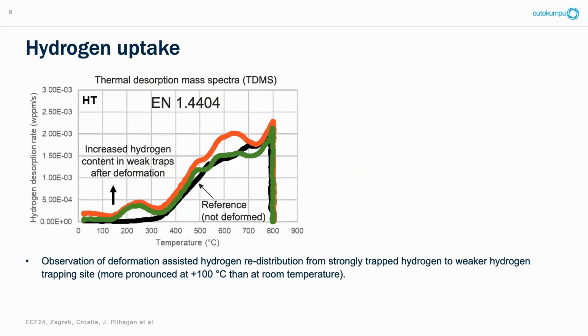And we also measured the hydrogen uptake, and we used thermal desorption mass spectrometry. So we heat up the sample and measure the hydrogen desorption rate. The black curve here is the reference, the non-deformed one. And the orange and green are the ones after testing in slow strain rate and also at 100 degrees Celsius. What we can see is that from the production, those austenitic stainless steels have quite a high hydrogen content, but it's mainly located in the high temperature part, which is the strong traps or deep traps. And we see that upon deformation, it seems like you redistribute some of the hydrogen to the lower traps. You can see the peak here at around 250 degrees Celsius.